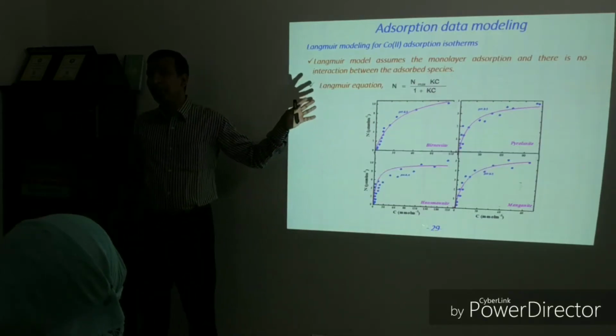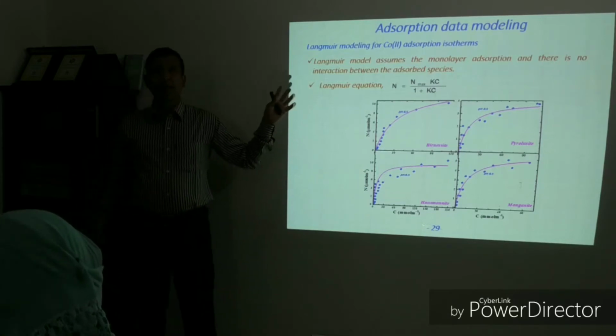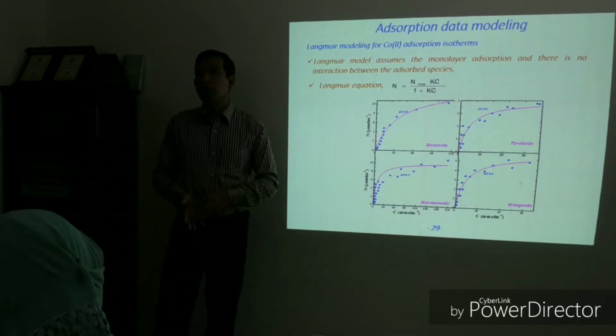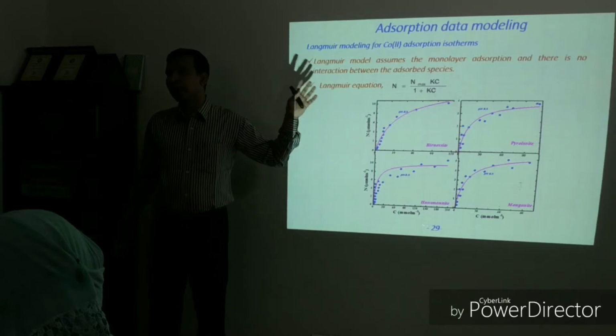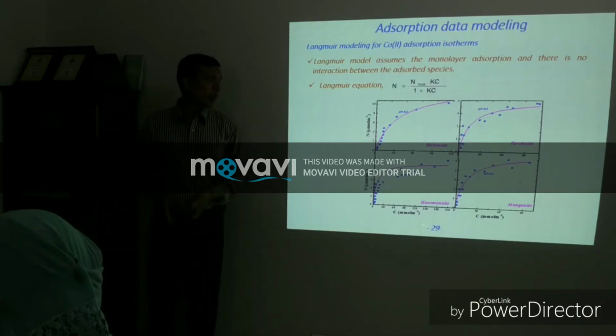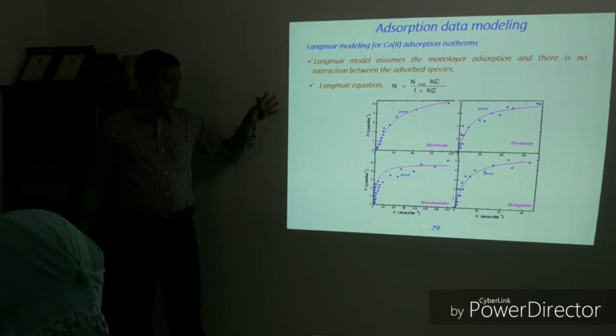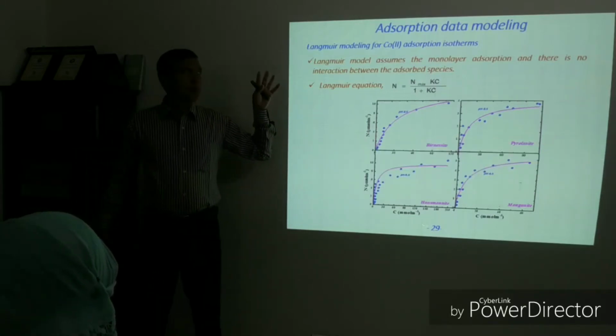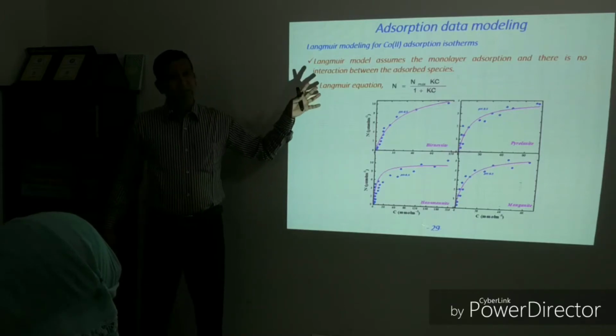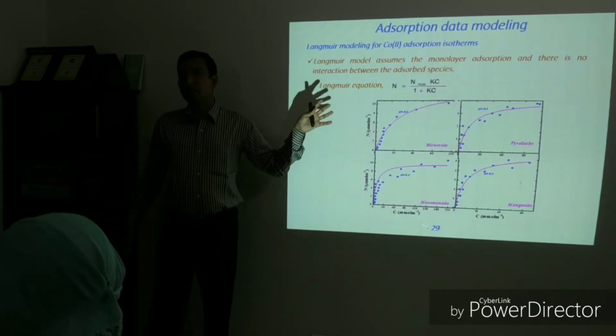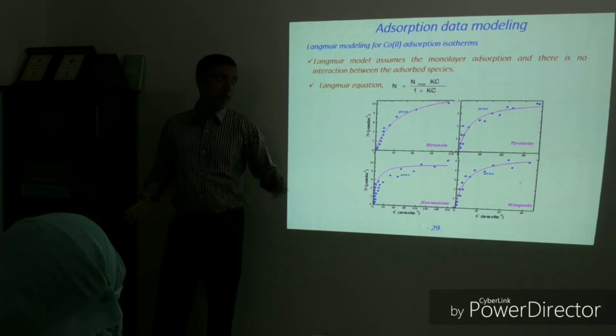Then we have studied adsorption data modeling using pseudo first order, second order, Langmuir and Freundlich isotherms. In most cases, the pseudo second order equation fitted the experimental data very well, and the Langmuir model also explained our data very well, implying that most metal ions and humic acid adsorb onto a homogeneous surface by forming a monolayer.